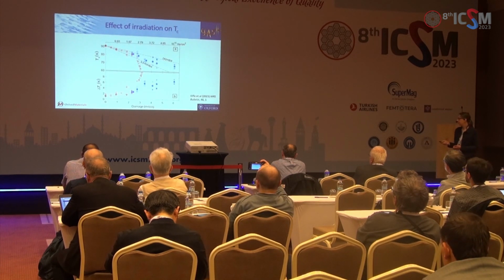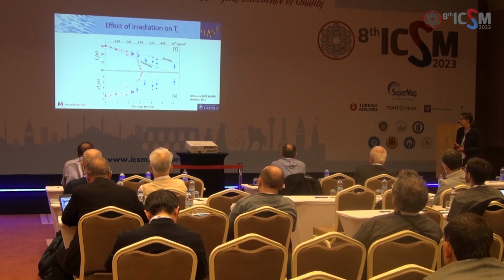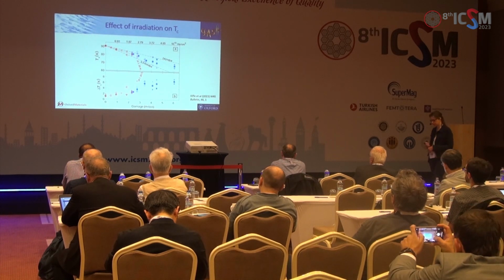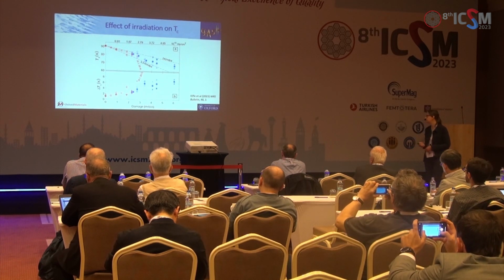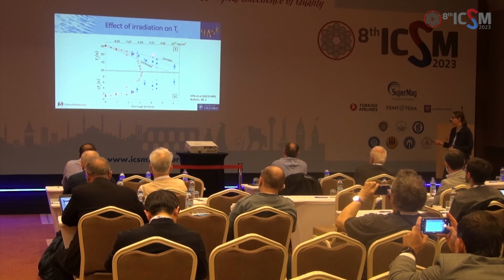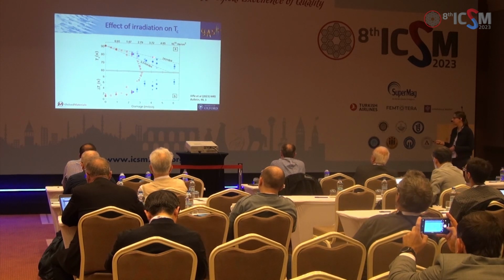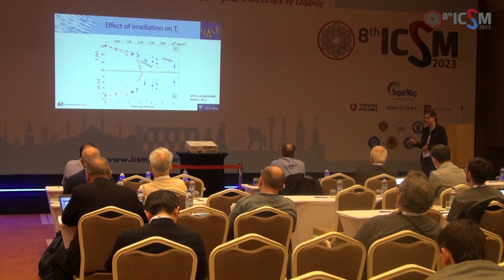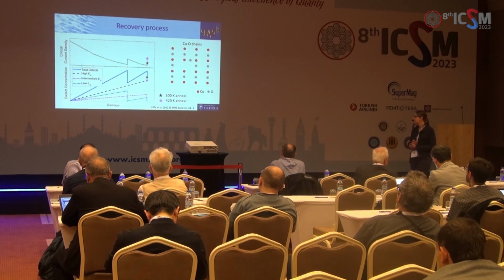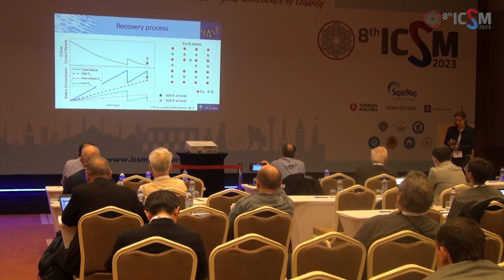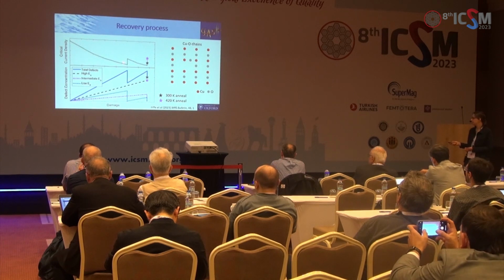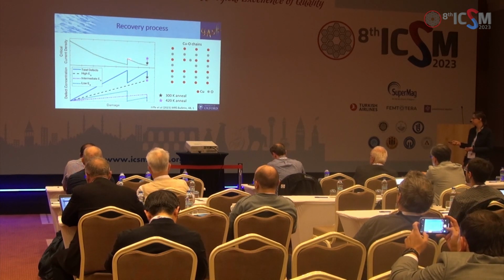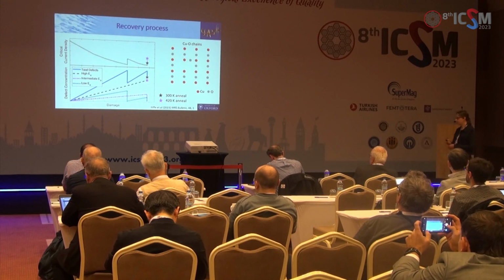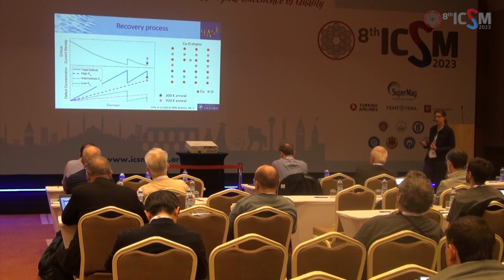TC does a similar thing. I won't spend very long on it, but you can compare what happens to TC degradation in the room temperature and the cold irradiations. And we also get this recovery in TC when we go to room temperature if we've cold irradiated them. So what do we think is happening? If we look at the critical current density, it does this. We go to room temperature and it gets a bit better, we irradiate again. What we think is happening is that we've got different kinds of defects being put in there during the irradiation.